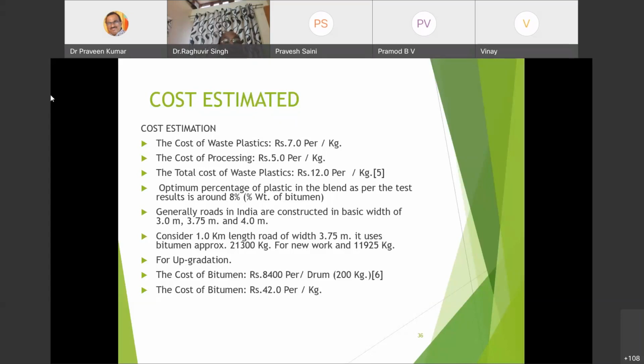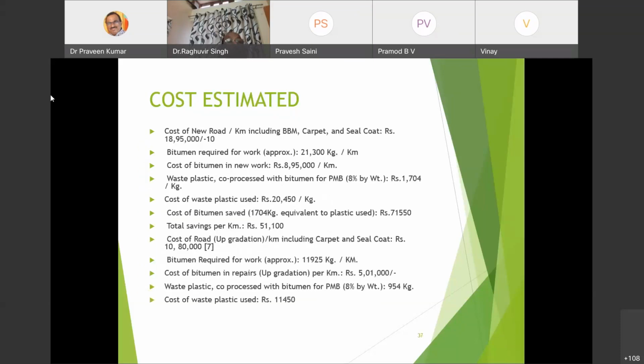Sir, generally roads in India are constructed in basic widths of 3.0 meter, 3.75 meter, and 4 meter. So consider a 1 kilometer length of road of width 3.75 meter. It uses bitumen of approximately 21,300 kg for new construction, and for upgradation a lower quantity. The cost of bitumen is Rs 8,400 per drum of 200 kg, that is Rs 42 per kg. The cost of a new road per kilometer, including DBM, carpet, and seal coat, the bitumen required for one is approximately 21,300 kg.